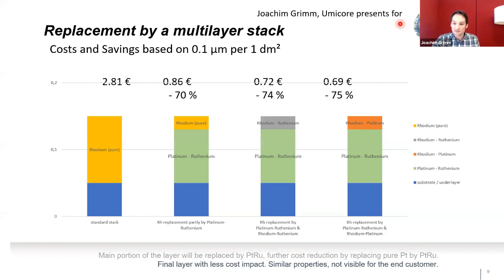And last but not least, you can do the additional step. Instead of the rhodium-ruthenium, you do the rhodium-platinum on top, where we have the mixture rhodium-platinum 50-50%, and then the platinum-ruthenium underneath, where you have it flexible in the thickness, what you want to go, or how high the thickness shall be in the intermediate layer. And you do your whitest layer on top, depending on if you want to go for the pure rhodium or want to have the additional saving, up to 75% is possible in that way.